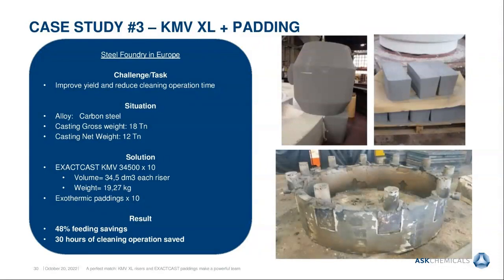In the end, the challenge was really not to change the geometry of the original casting and be able to feed all the casting with the risers on top. In the end, compared to the original traditional feeding systems, they were able to reach this 48% of feeding savings. And the most important thing was the 30 hours that they saved due to the cleaning and fettling operations. In the end, this foundry was much faster from the foundry process to the delivery process. So in the end, they really have a lot of benefits using this combination of products.